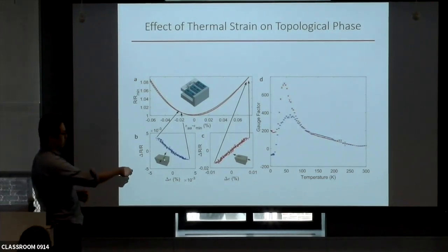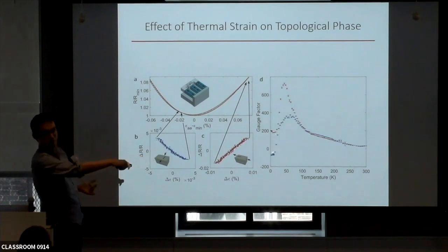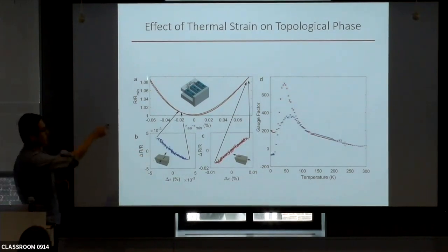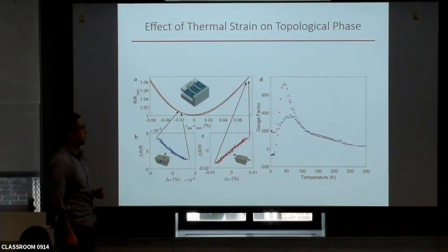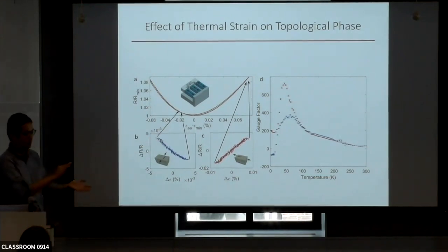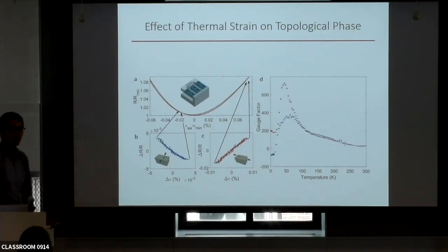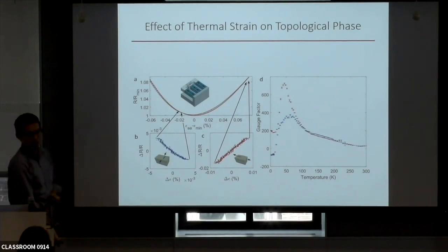And it turns out that the crystal glued this way and the crystal glued that way are seeing different topological phases, based on our interpretation of strain-induced topological phase transition. So very likely, different people do different measurements, glue on different substrates and prepare in a different way. And the crystal itself probably varies from batch to batch, so they can get mixed results.